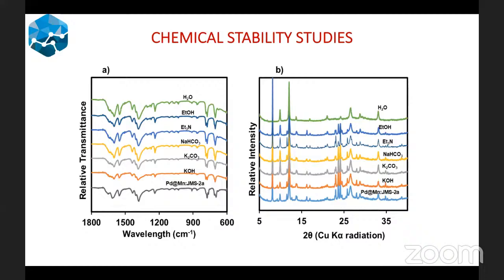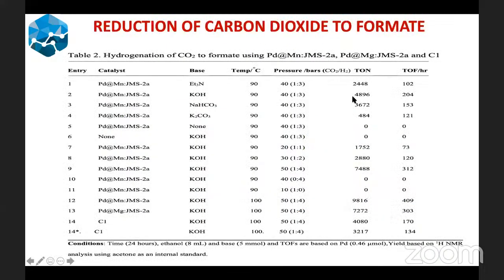Potassium hydroxide gave the highest turnover number of 4,896 under these conditions of 90 degrees Celsius and the pressure ratio of 1:3. This was very interesting. And again, the first base that was used also showed some activity, which is almost half that of potassium hydroxide.